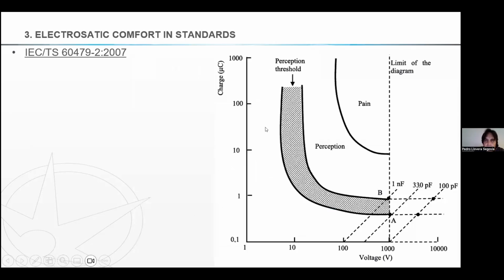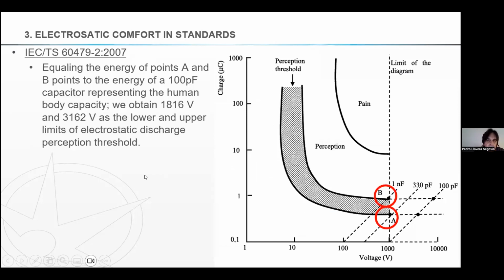If we take this curve, it's not exactly adapted for comfort problems because we are around 100 or 150 picofarad charging, and this point is outside the curve. The 100 picofarad is not on the graph. We can extrapolate. If we consider the closest points, 1 nanofarad, point B, or 330 picofarad, point A, in the energy of these 2 points, and we try to extrapolate to a human person, then we get a level of perception between 1,800 volts and 3,000 volts, more or less.